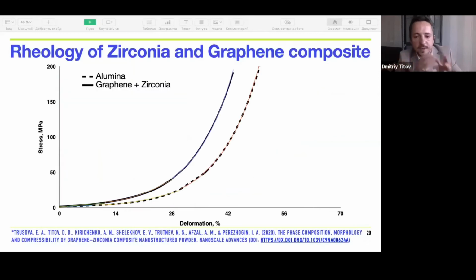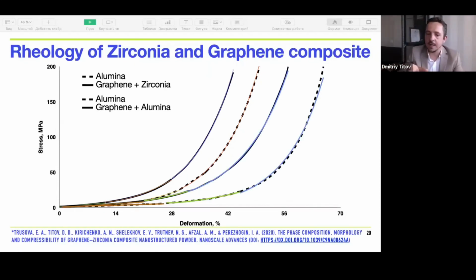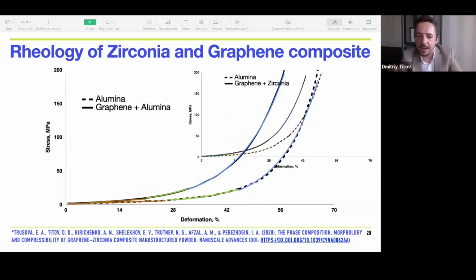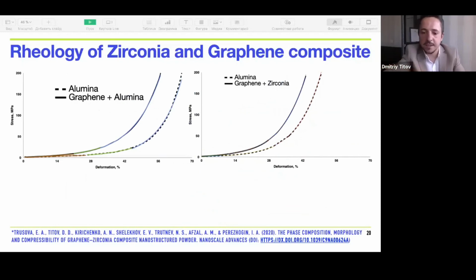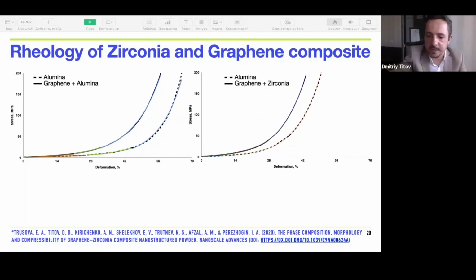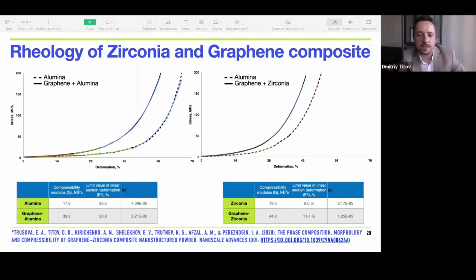The curves for the composite with zirconia oxide are presented here. Let's compare the rheology curves for both oxides. Of course, the particle size, shape, and nature of the powder affect the curves. However, in both cases, a similar tendency is observed for the effect of graphene sheets on the rheology. At the first stage, the slope of the curves increases and the compressibility modulus is 2 times larger for the composite than for a pure oxide, I'm sorry. And below you can see the calculated constants for the oxides and composites.